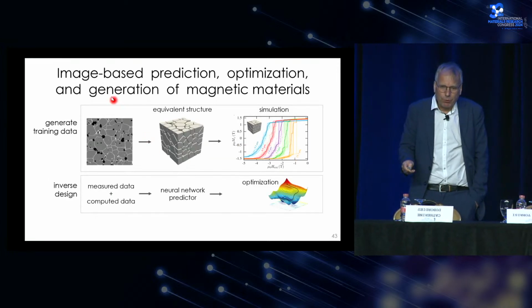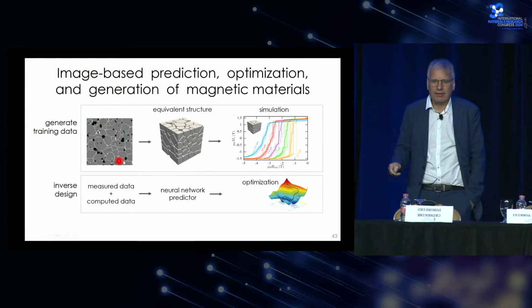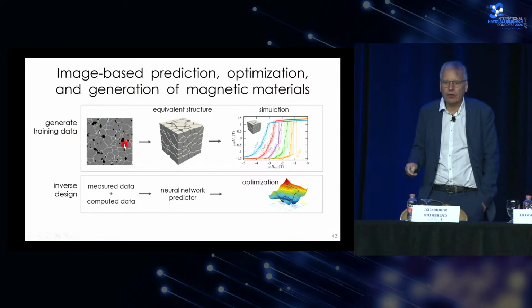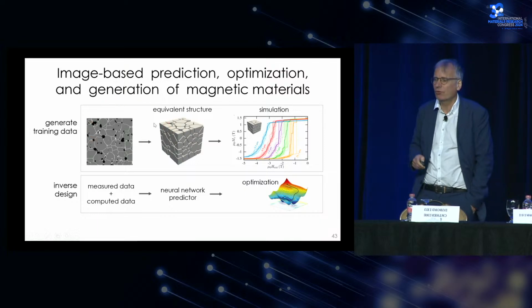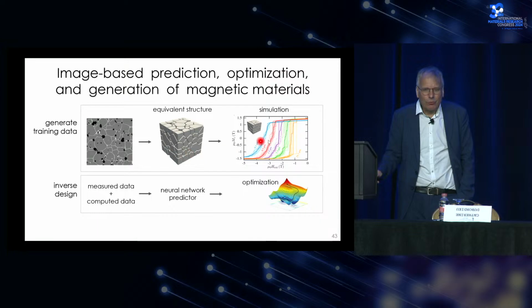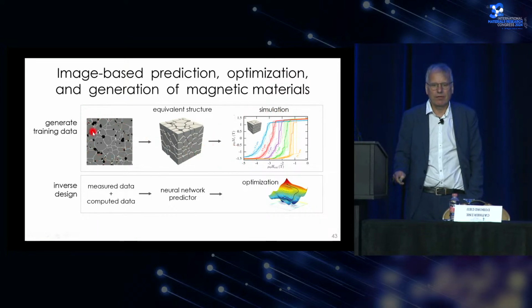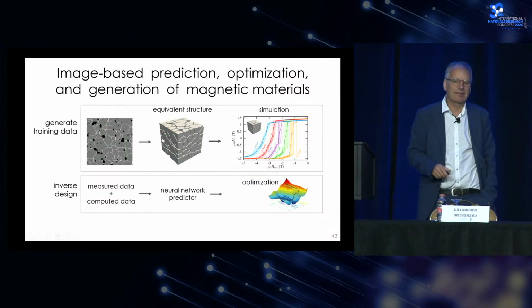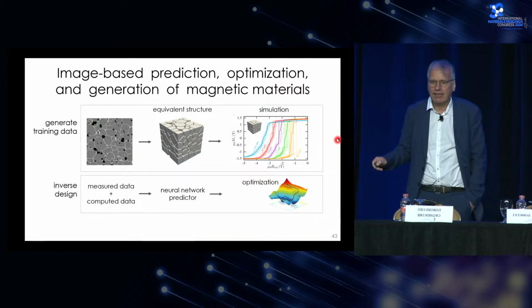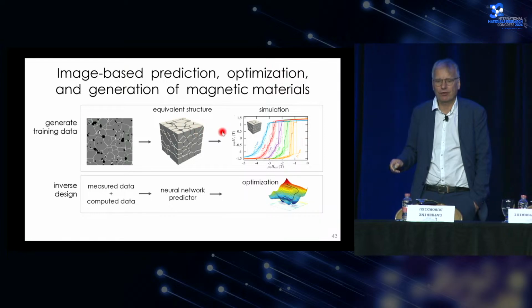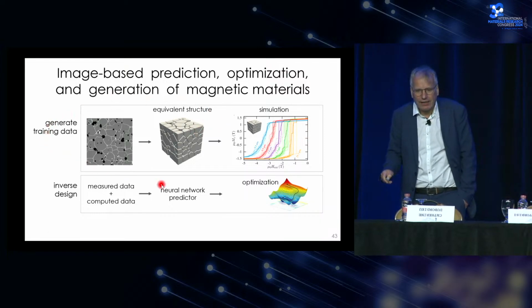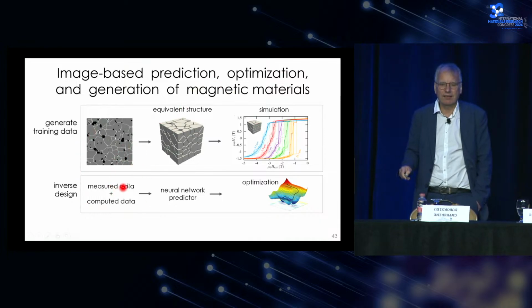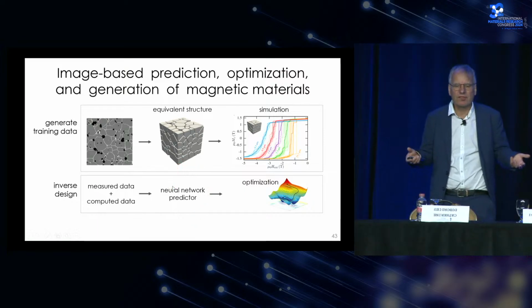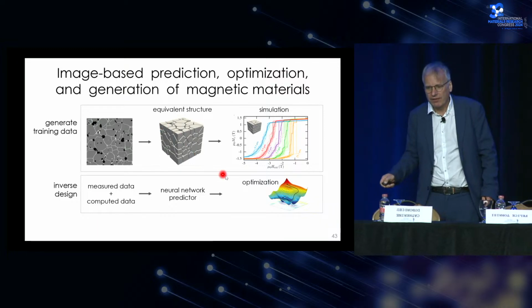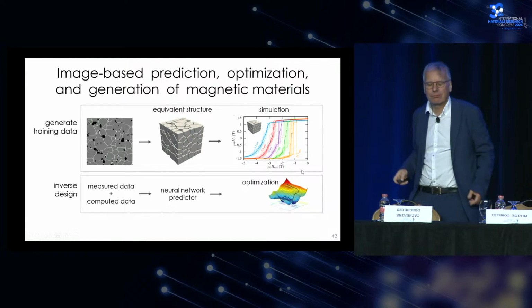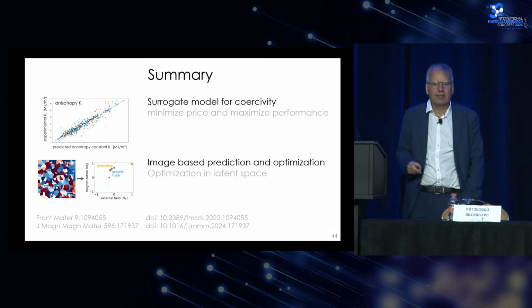So what we propose to do now is generate training data, and we can generate image-based training data not only on simulation, but we can make a relation to experiments by doing micromagnetic simulations that resemble real microstructures. And then we can tune and change this artificial synthetic microstructure and, for example, change the grain size or the aspect ratio of the grains. If we collect a lot of data, measured data and computed data, we can feed this into a neural network, and then we can use this neural network as a surrogate model for optimization to create magnets according to our wishes, our design. With this, I'd like to summarize.